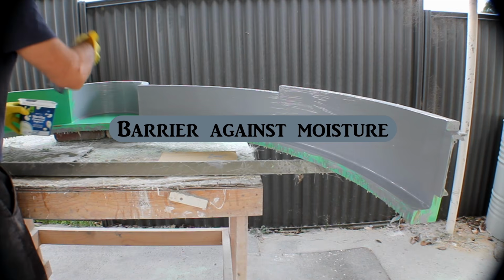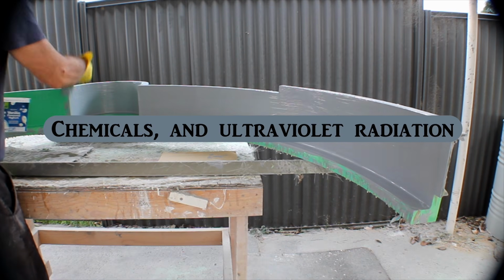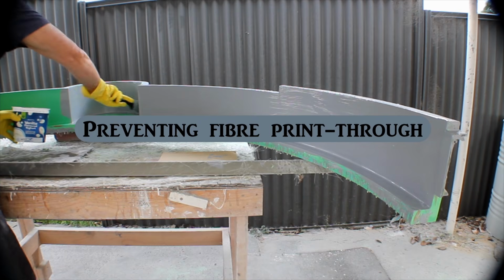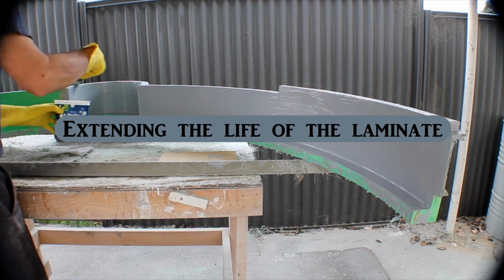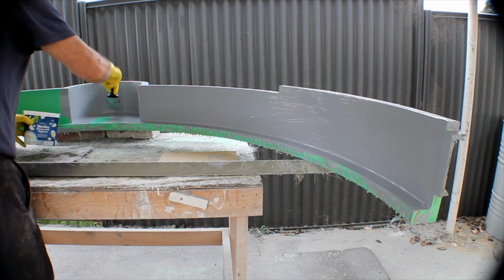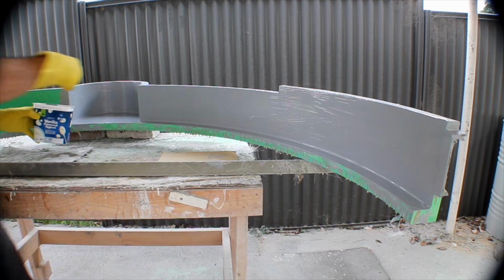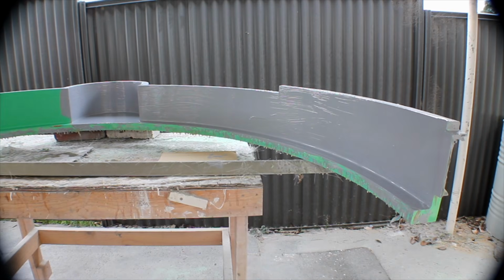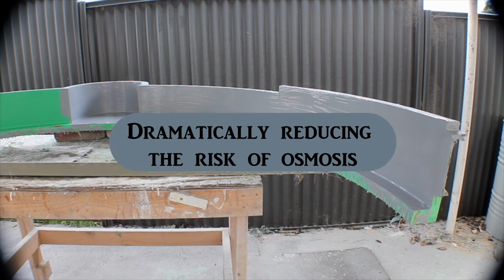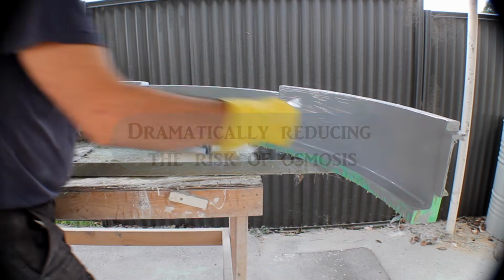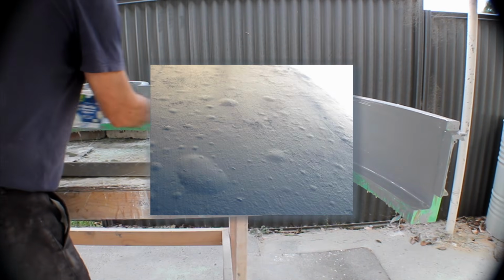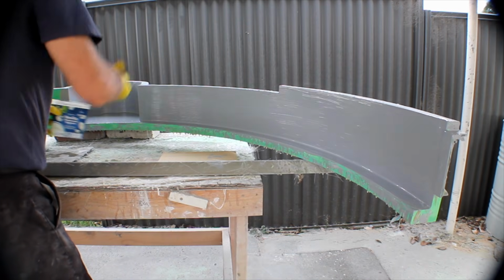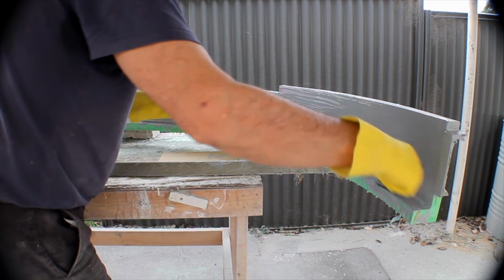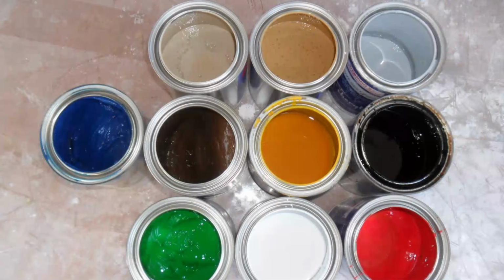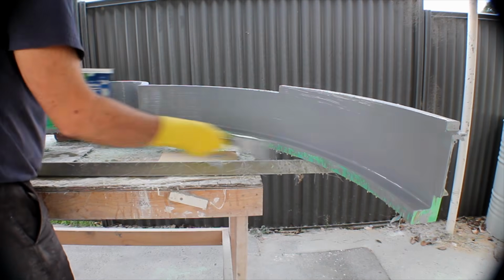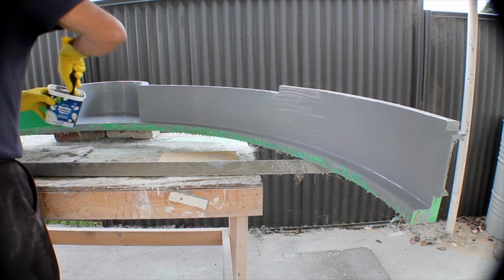Gel coats act as a barrier against moisture, chemicals, and ultraviolet radiation, preventing fiber print-through and extending the life of the laminate. Clear gel coats, which contain no pigment, provide even greater resistance to water penetration. When paired with a vinyl ester resin laminate, they can dramatically reduce the risk of osmosis, those small, blister-like defects that form under the surface in boats and tanks. Gel coats are also abrasion resistant, maintain a high-gloss finish, and come in a wide range of colors. For outdoor use, UV stabilizers are commonly added to protect against chalking or fading.